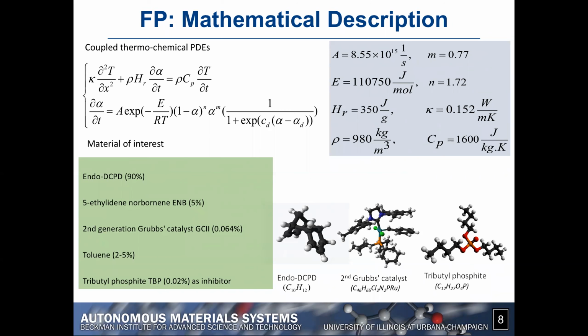d alpha/dt is described in the second equation, and that's the pure kinetic model that is extracted from measurements, from the DSC measurements performed on this polymer system. And then typical values that you have in this model are listed on the right-hand side. The material of interest, as I mentioned, is dicyclopentadiene, DCPD, with Grubbs catalyst.